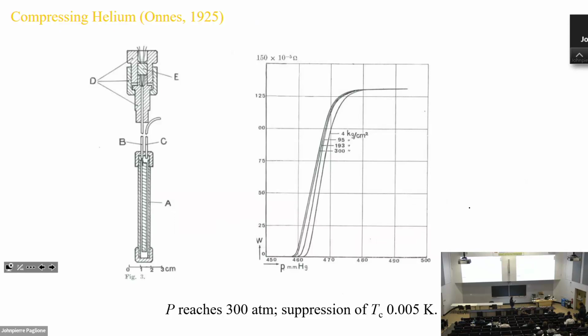So this is, at the time, the setup. The idea is very simple. They use helium to cool down the sample. Then if they squeeze helium gas into the chamber, you increase the pressure. If you look at the setup, there are two tubes going down to the sample chamber. One has some electrodes coming out for the experiment. The other one, you can squeeze helium gas in there.